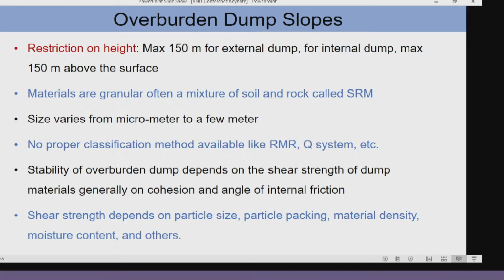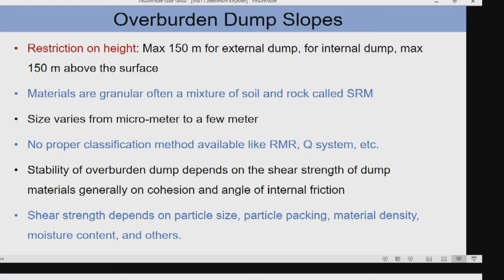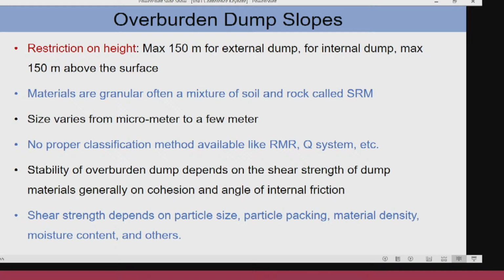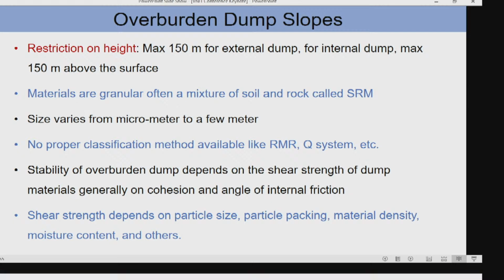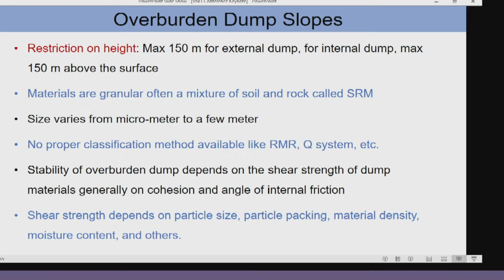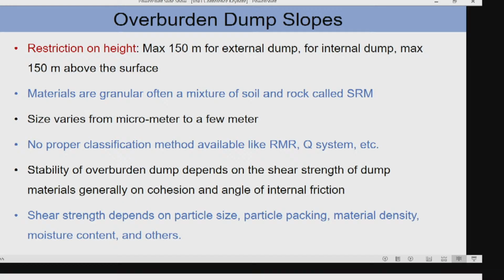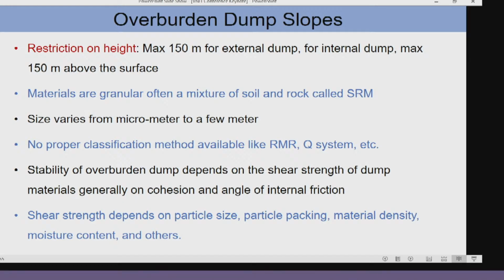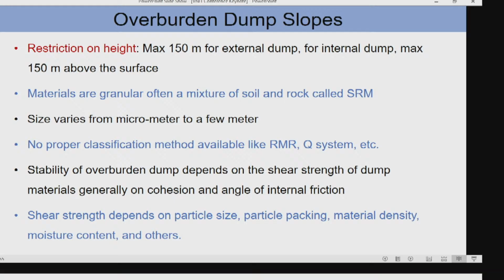Our experience shows that we are not able to recreate a naturally compacted dump in the lab. When we check the density in the field, it is about 2.2 to 2.4. But we could not achieve it in the lab. We tried many different ways and could go up to 1.9. So nature makes this compaction much better. Since we are not able to match the density, the extrapolation of results like cohesion or friction angle from lab to field may not be accurate. That is one of the reasons that sometimes laboratory tested results don't work in the field.